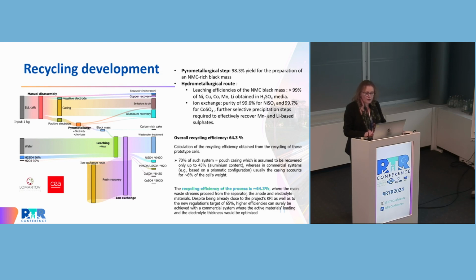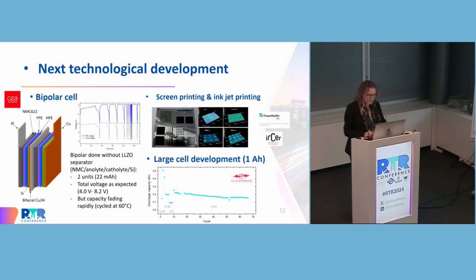The overall recycling efficiency is lower due to the fact that in this pouch cell we have also some aluminium and also different polymers that are limiting the recycling. But if we increase the capacity size of the cell, we are also able to decrease this packaging impact. From this project, we have also developed some new technology, new knowledge, and we have also initiated some work on bipolar cell as an example to increase the power of the technology.